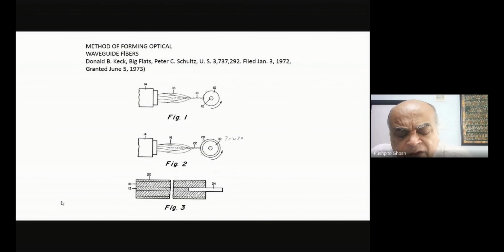Now this is actually an interesting approach, and what all of you should look at is that when you have this kind of a problem, and I asked you, what is the precursor? Obviously, we know that if I take volatile things, then they will mix uniformly. If I take two gases and I mix them, then I'll get a mixing of those gases. So what they realized was that silicon tetrachloride. What is the physical form of silicon tetrachloride? Does anyone know? And titanium tetrachloride? Liquid. And it's a very volatile liquid.